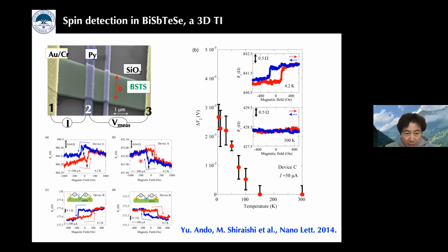And my group tried to detect the surface spin polarization due to the spin momentum locking in 2014. And at that time we used bismuth antimony tellurium selenide, which is a three-dimensional topological insulator, and we successfully detected the resistance hysteresis which comes from the surface spin polarization of the 3D topological insulators.